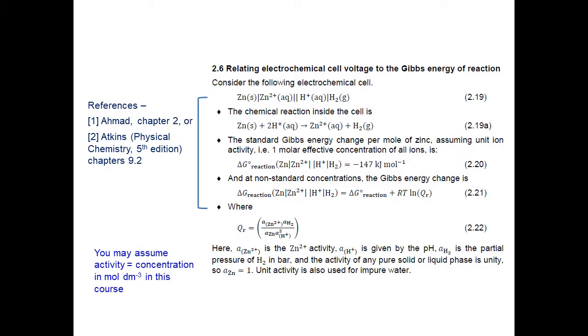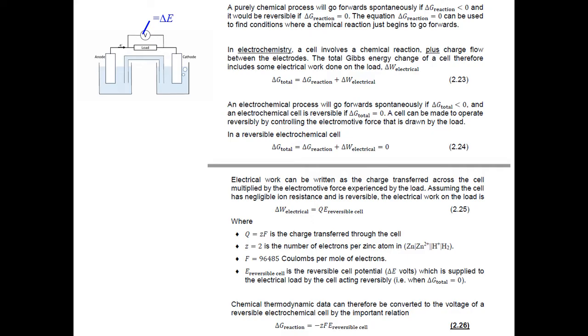So we're looking at, does a process go forward? A purely chemical process goes forward spontaneously if the Gibbs energy change, the delta G of reaction, is less than 0. And it would be a reversible process if the delta G of the reaction was equal to 0. So delta G of reaction equal to 0 is important because we can use it to find conditions where some purely chemical reaction just begins to go forward. In our work on electrochemistry, we're looking at a cell process, which involves the chemical reaction plus some electrical charge flow between the electrodes. Therefore, the total Gibbs energy change of an electrochemical cell includes some electrical work, as well as the reaction. We can write the total Gibbs energy change in an electrochemical cell as equation 2.23: delta G of reaction, plus some delta work electrical, some work done on the load by the cell process going forwards.